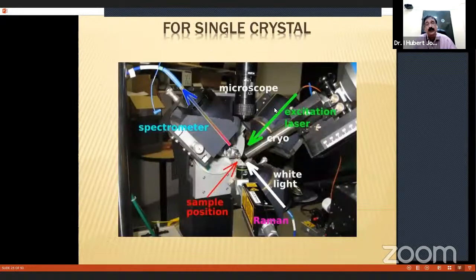Now, single crystal spectra. In a single crystal, you know there is an a-axis, b-axis, and c-axis. You can cut the crystal to any size and pass the laser radiation along either the a direction, b direction, or c direction. You can change it using a polarimeter. You can change the direction of the incident light and the direction of the scattered light, and the electric vector of the incident and scattered light, in any direction. This is done using a goniometer.